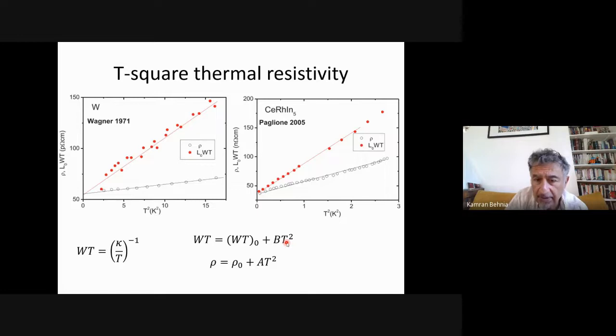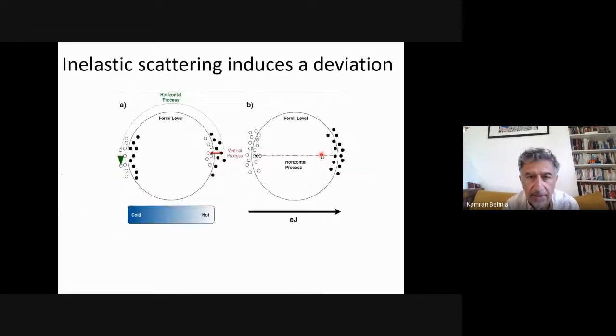Now, if you compare these two numbers, what is found is that at zero temperature, you recover the Wiedemann-Franz law, in the sense that the residual electrical resistivity and the residual thermal resistivity are correlated with each other. But if you look at it, the slope is larger. So you have a deviation from the Wiedemann-Franz law at finite temperature. And this is known and has been understood as the fact that you have horizontal processes.